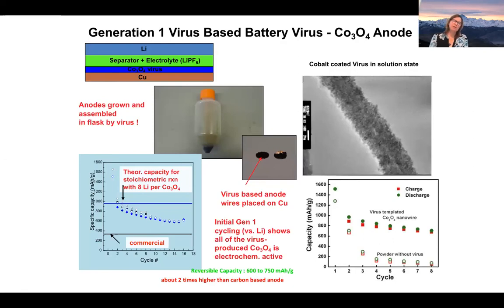And what we're going to be looking at is the specific capacity versus the cycle. So this is the ability to store lithium in the lithium-ion batteries. And so you want to have a higher capacity, and you want to have, obviously, a long cycle life. We had very short cycle lives when we first started this, but basically, we find the right virus sequence, we get it to grow the material of interest, we spin it down, we make an electrode out of the material, and then we measure it.